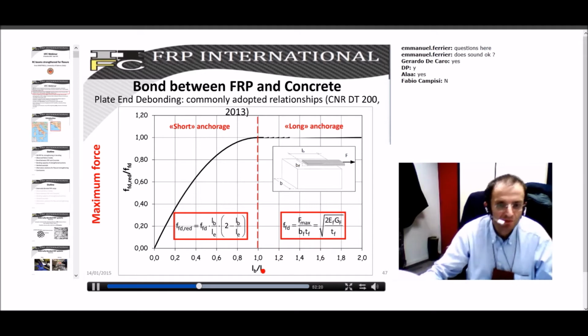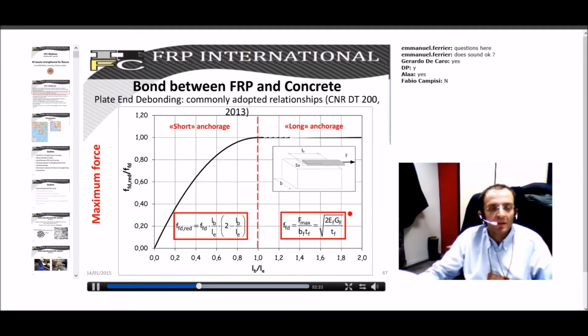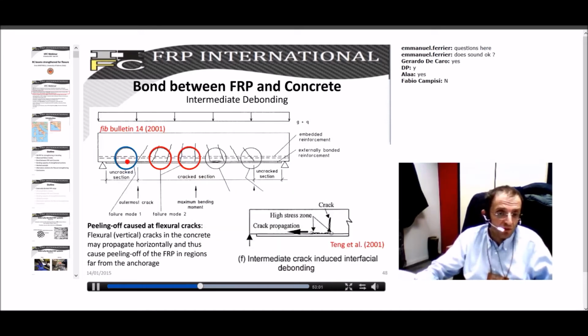So you have these two situations, a clear border once you have defined LE. If the bond length is lower than LE, you have a lower force, F maximum, and a lower bonding strength, FD. Here, if LB is equal to or longer than LE, you attain this F maximum, which means you attain this debonding failure. So this is the way of describing the bonding phenomenon in a pull-out test, which conceptually corresponds to the situation you have here at the end.